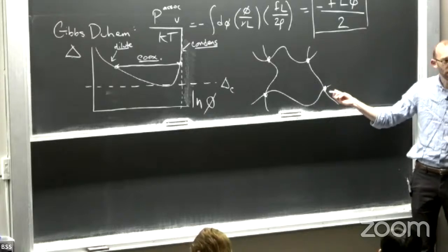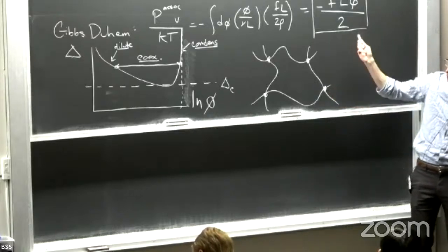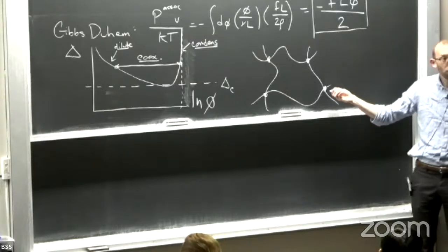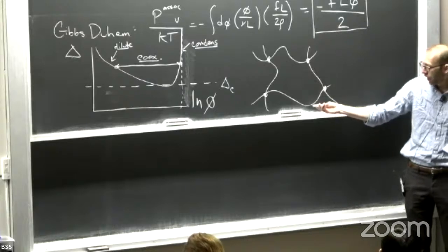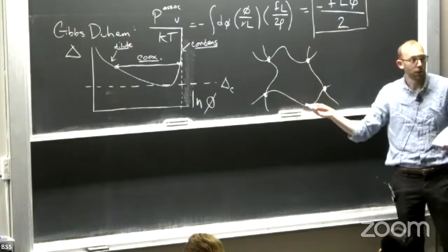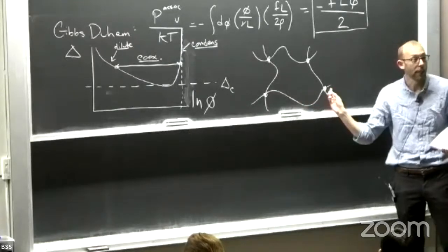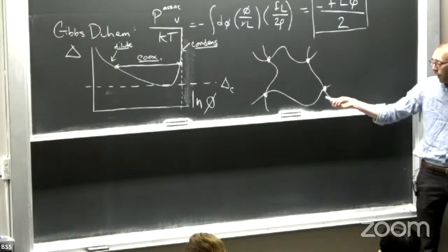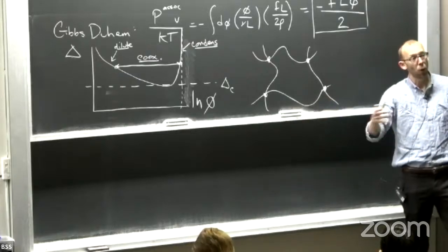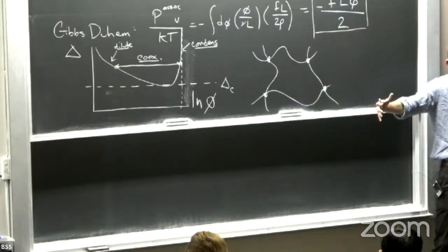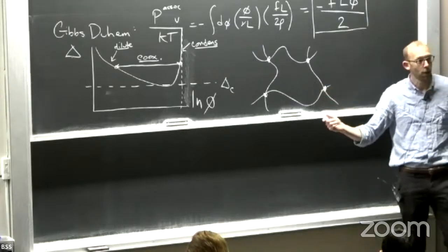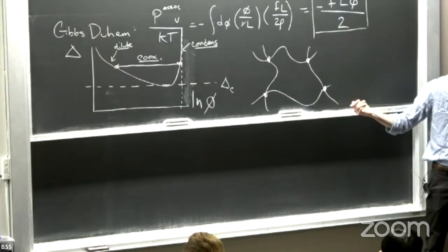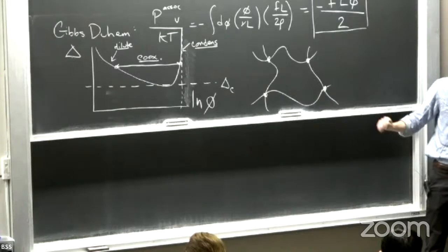But this argument that the excess chemical potential has uncorrelated positions and orientations of monomers will break down if you have very non-mean field like interactions in the regions between these binding sites, right? And so in particular, if you have chains here that are in the swollen chain regime, they want to expand and push these binding sites far apart. Under those conditions, then the sort of mean field picture can break down. Right? So that's one possibility.